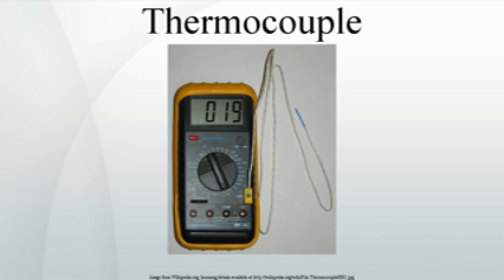In the case of Type K thermocouples, manganese and aluminium atoms from the KN negative wire migrate to the KP positive wire, resulting in a downscale drift due to chemical contamination. This effect is cumulative and irreversible. A short-term cyclic change in thermal EMF on heating in the temperature range circa 250 to 650 degC, which occurs in types K, J, T, and E thermocouples.